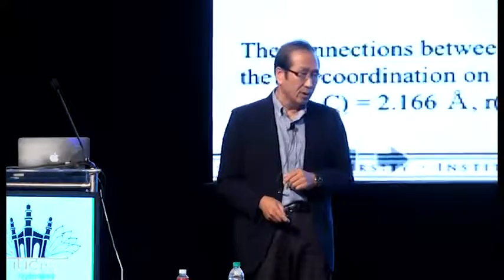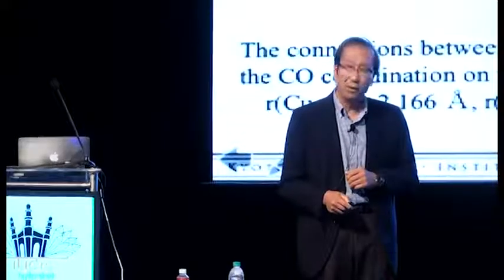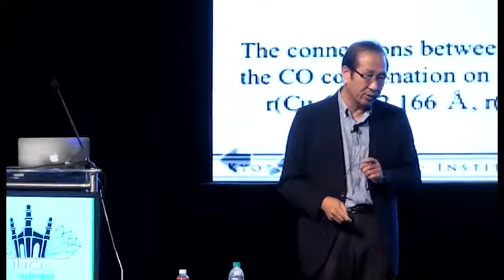That's a big difference. So we determined the crystal structure, and the small channels show just an open gate like this. What's happening? In this case, the CO coordinates to the copper 2+. Coordination is very important in this case. But I have to remind you, this is kappa 2. Usually kappa 1 has a strong interaction with CO, but not kappa 2, because the energy is very small, 20 kJ per mole.